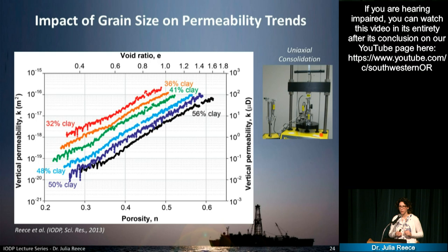And this is, again, the ability for fluids to move through the sediment. And so here we are now looking at this parameter, the permeability versus the porosity. The way that we read this is we are starting here at high porosities, and then as we start to compress the sediment more and more, the permeability is being reduced along with the porosity. And so in black again, we have the clay, the finest grained mixture, and in red here, the coarsest sample.